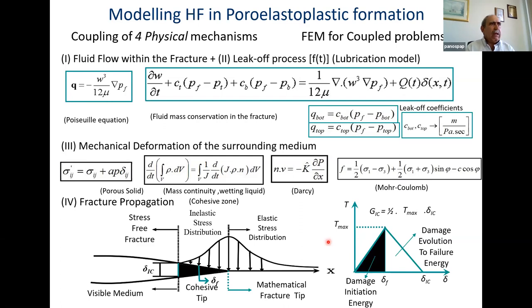We extended this work by looking into the role of the pore pressure and the leak-off in the formation as well, and so we look at also some of the sensitivity of the results on the fracture criteria of the cohesive model. And just to say for people that do such modeling, the shape of the softening of this curve is not very important, if it is linear or exponential. What is important is the area under the curve, which is equal to the strain energy release rate. We found also that the initial slope, the stiffness, could be important in hydraulic fracture.